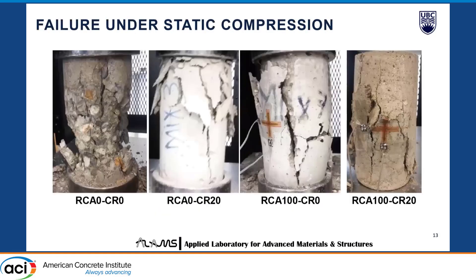These are a few of the failed specimens. The rubberized concrete mixtures held up well even after failure, whereas the conventional concrete mixture just crushed under the highest load. With 100% RCA and 20% rubber, the cylinder remained quite compact even after failure, as visible in the rightmost picture.